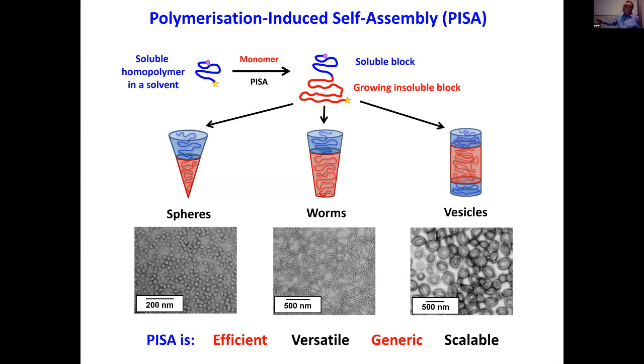It's very versatile in that it works for a wide range of vinyl monomers: methacrylics, acrylics, acrylamides, methacrylamides, vinyl acetate, styrene, etc. It's generic, as I've already mentioned. It works for various different types of media, not just aqueous: polar solvents such as lower alcohols, alkanes, supercritical fluids, etc. And it's scalable. One of our industrial sponsors has taken a 5-gram formulation from our lab, gone all the way up to 100,000 gallons, and then not quite commercialized it, which is pretty frustrating.